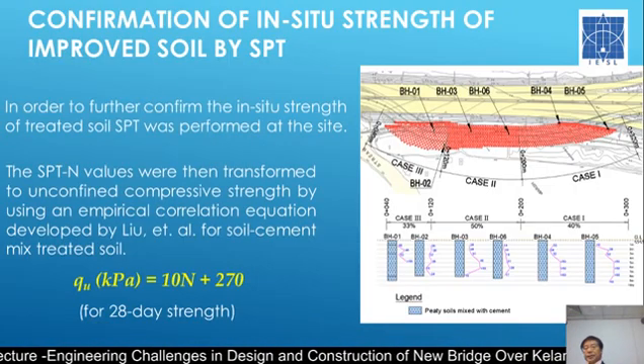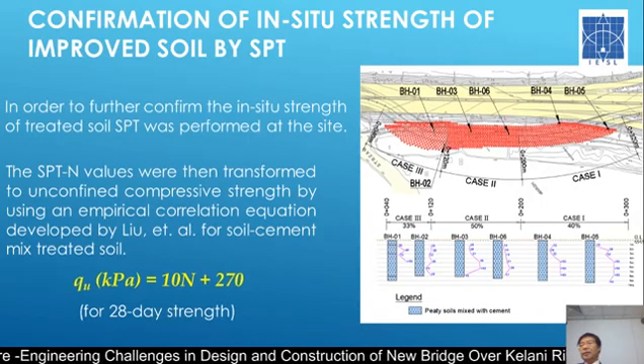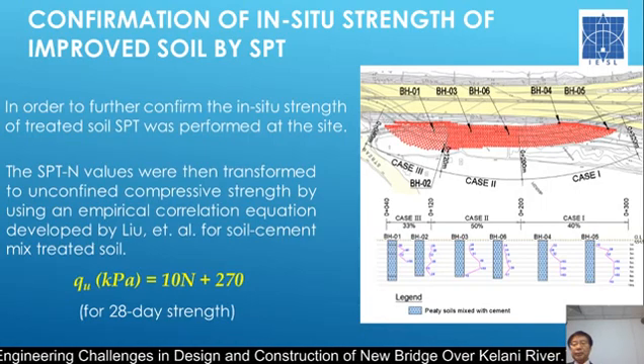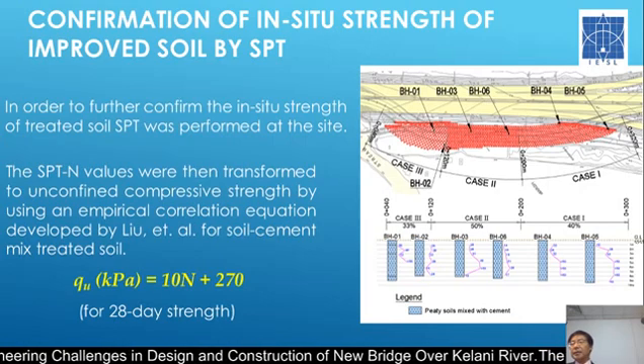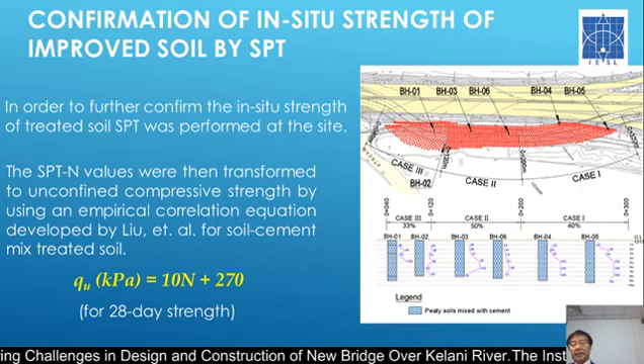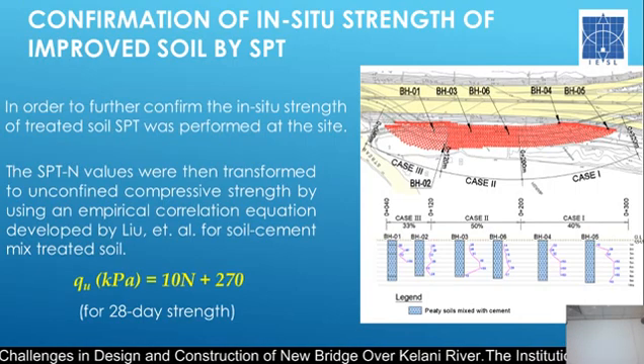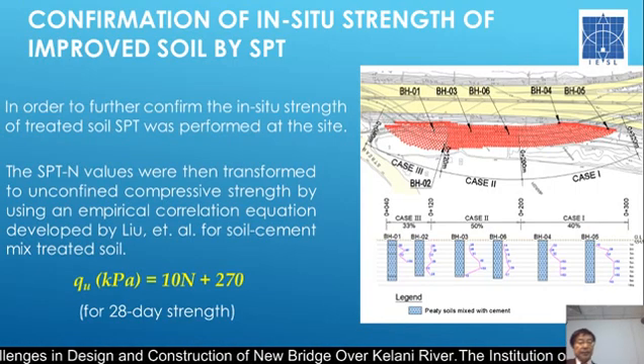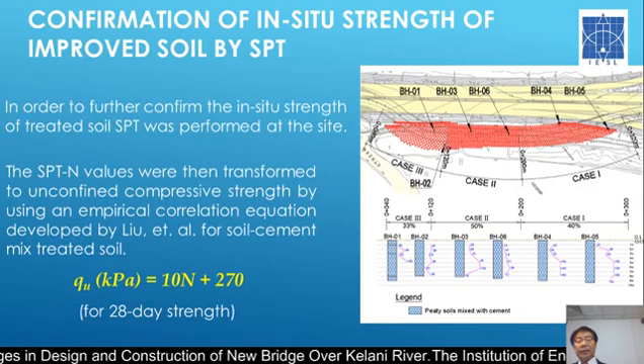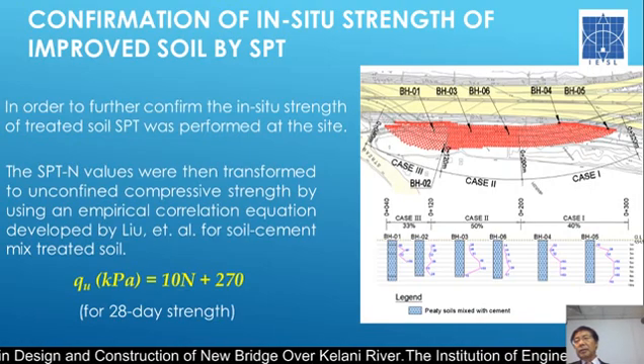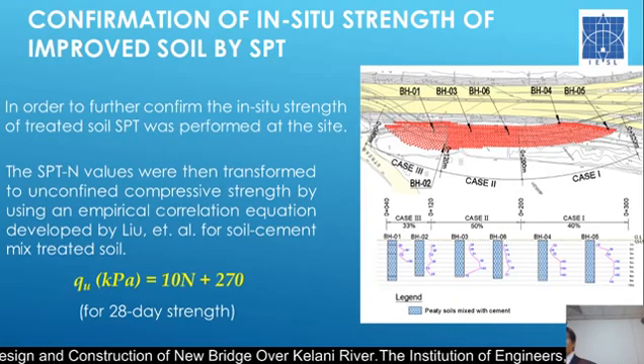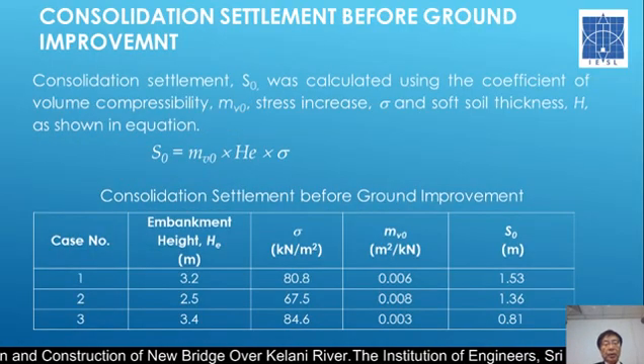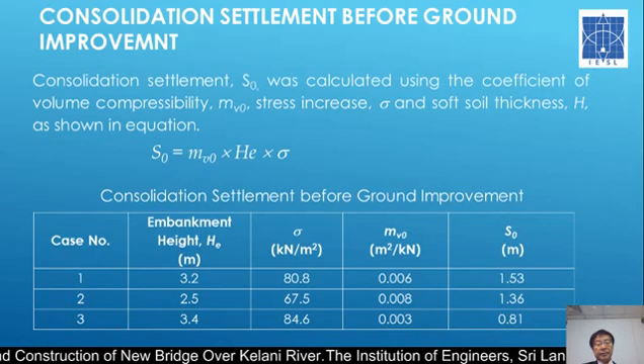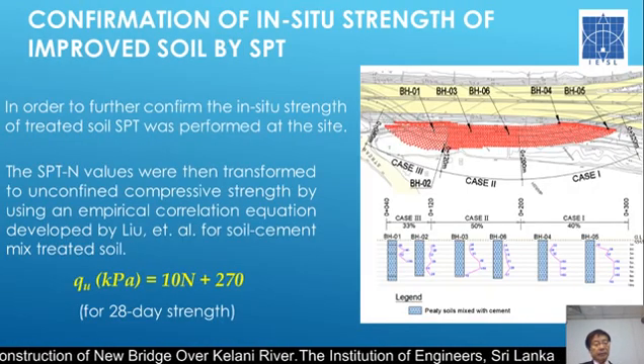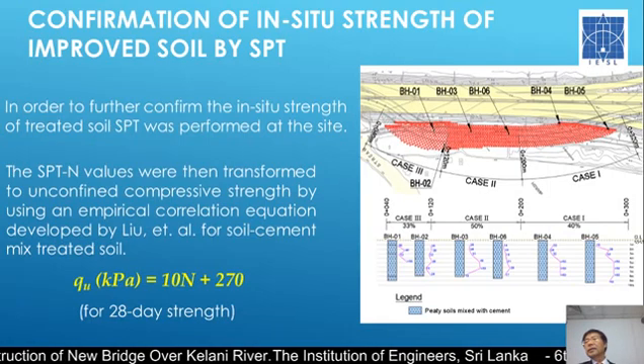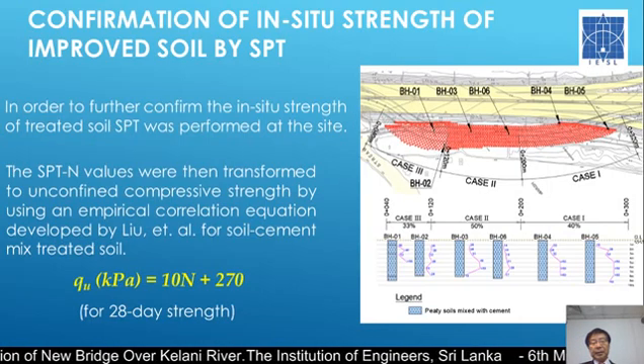So after we have done this operation, we checked what is the actual strength of the improved soil. That is done by the standard penetration test at the site. We did that for each of the 3 locations. And there is an equation to convert the N value to the uniaxial compression test strength, as in that equation. So that gives, and we proved that the strength is sufficient, much higher than we expected.